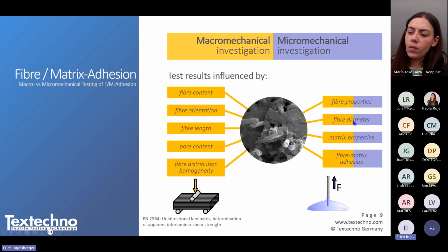We already could measure the fiber properties and the fiber diameter with the Favimat. The Favimat also is part of this fiber to matrix adhesion test system. The matrix properties you can either get from the provider of the matrix or from literature, and what is left over is only the fiber to matrix adhesion. This is what we want to measure. I would like to introduce this system in detail.